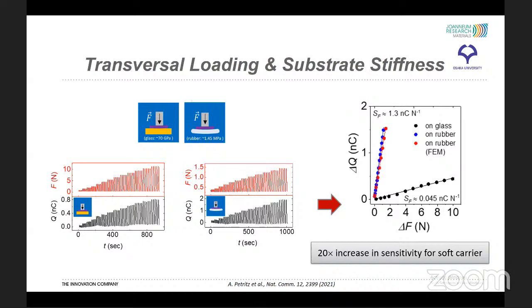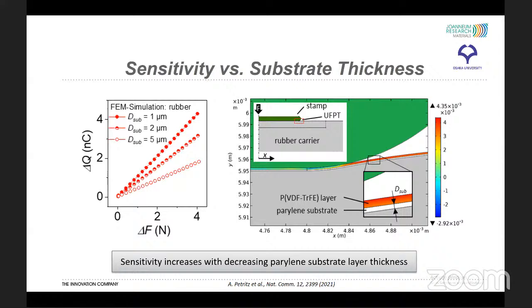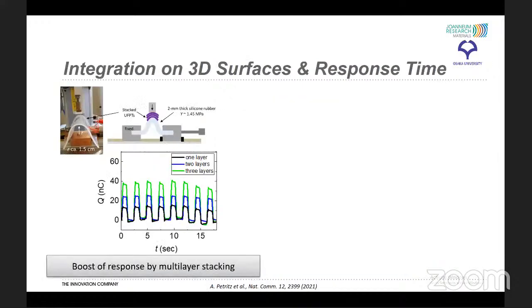And this behavior and increase in sensitivity was also confirmed by FEM simulations. Furthermore, the simulations also reveal that the sensitivity increases with decreasing Parylene substrate thickness. Interestingly, the simulated strain in the piezoelectric layer is largest near the edge of the stamp.